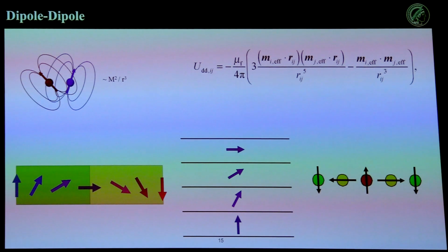So then there's the dipole-dipole, and dipole-dipole creates non-collinear textures in several different ways. One is this case here, where you have some material and you say, I want my magnetization to be up, and over here I want my magnetization to be down. In dipole-dipole, you can see very quickly, there's a minus sign here and there's a dot product, and that already says all these guys want to point in the same direction. But also, because of the way it's written, you have these symmetry terms between the atoms. So if you have more atoms to the left and right of you, then you want to point with those guys in a certain direction compared to pointing to the guys above.